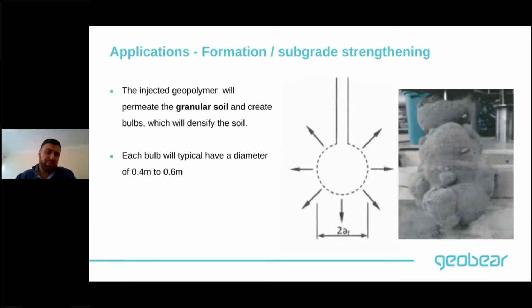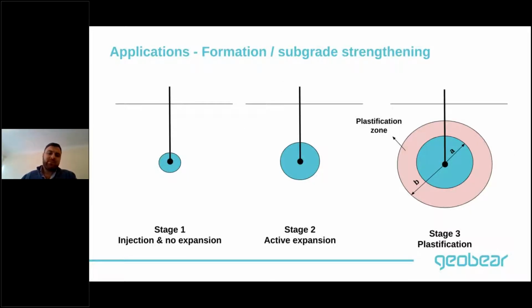However, in granular soils, the mechanism is completely different. When you inject geopolymers in granular soils, let's say some sort of fill material that is quite loose, you tend to create these sort of bulbs. And these bulbs will have a diameter somewhere between 0.4 to 0.6 of a meter. What these bulbs will do is basically expand and start compacting all the soil around them. And as a result, you will increase your compaction and your relative density, and therefore you'll end up with higher strength.